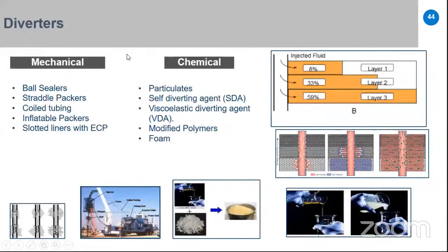So diverters, we have two types usually used in matrix acidizing. We have mechanical diverters like coiled tubing sealer. We use coiled tubing as a mechanical diverter. We have inflatable packers, and we have a slotted liner with external casing packer. All of these can provide a means of diverting during the job. We also have chemical diverters like particulates, such as salt, resin, and benzoic acid flakes. We also have in situ gelled acid like self-diverting agent SDA, viscoelastic diverting agent VDA, modified polymer, and also foamed treatment.